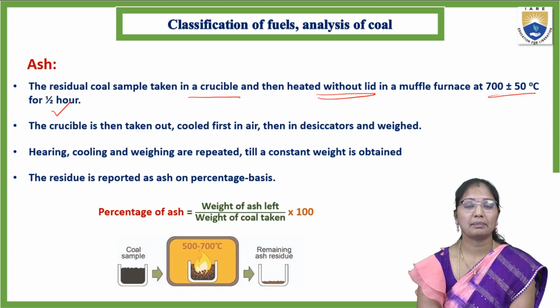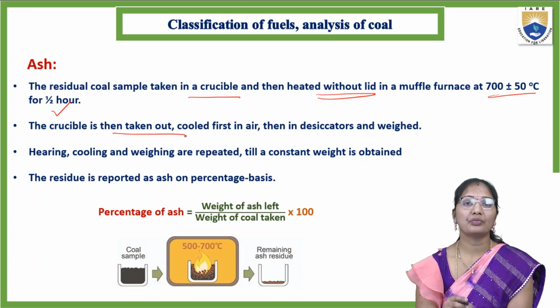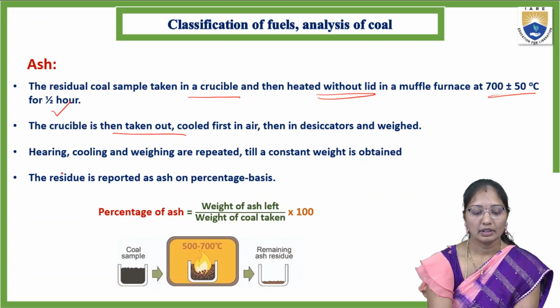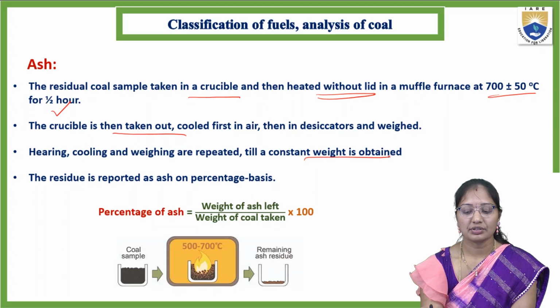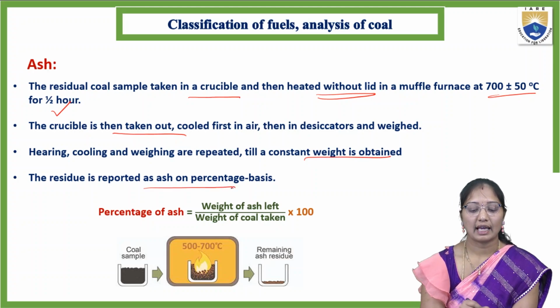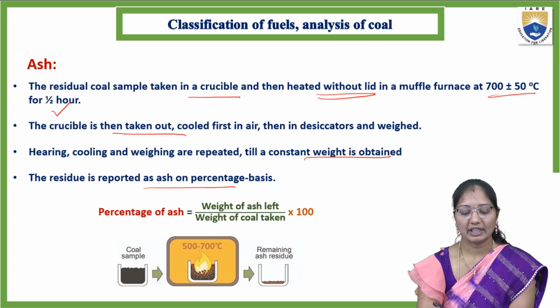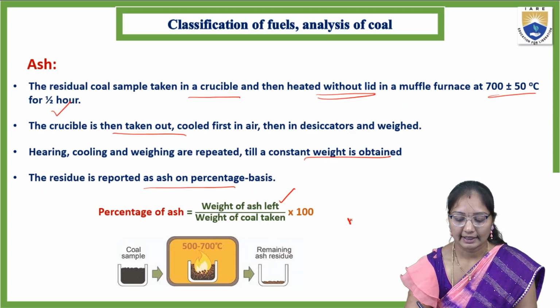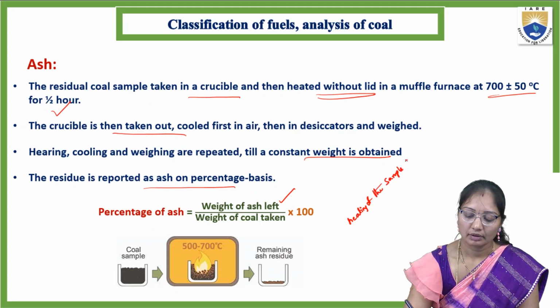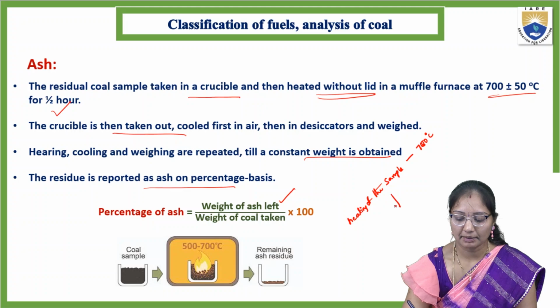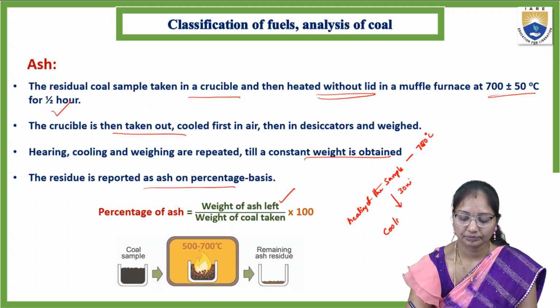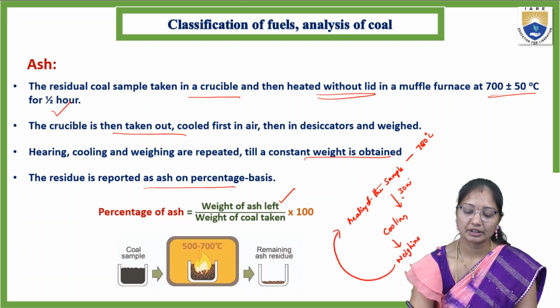Once the half hour is completed, the crucible is taken out, cooled first in the desiccator and weighed. Heating, cooling and weighing are repeated till a constant weight is obtained. The residue is reported as ash on a percentage basis. We repeat the procedure: heating the sample at 700 degrees centigrade for 30 minutes, cooling, weighing, and again heating for 30 minutes, cooling, weighing.